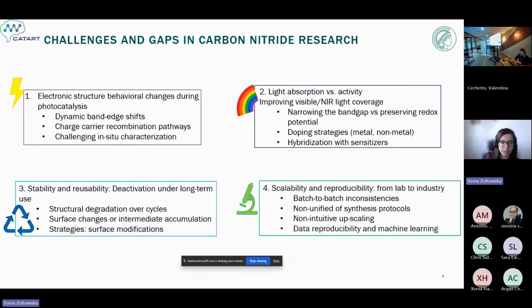But like in any type of material, we are facing a lot of challenges and gaps in the research. The challenges we can divide mainly into 4 different groups. First of all, the first challenge is related to electronic structural behavioral changes during the photocatalysis. So now we are trying to check what the dynamic band edge shifts are, what the charge recombination pathways are, and of course we are facing challenging in situ characterization. Carbon nitride absorbs visible light, but it does not have very good coverage of the entire visible spectrum. So we are trying to narrow the band gap and preserve the redox potential. Therefore, we are coming to doping strategies or some hybridization with sensitizers.